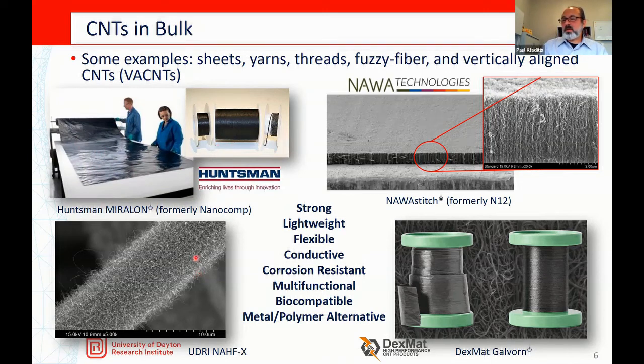And then the University of Dayton Research Institute was a pioneer in making carbon nanotube-based improvements. And right here is a scanning electron micrograph of a single carbon fiber with carbon nanotubes growing off of it. What we do at UDRI is we can take whole 60-inch wide rolls of carbon fiber cloth, send them through a reactor we have, and grow these carbon nanotubes on all the carbon fibers throughout the cloth. And then we can use that to lay up composites and increase electrical and some mechanical properties.